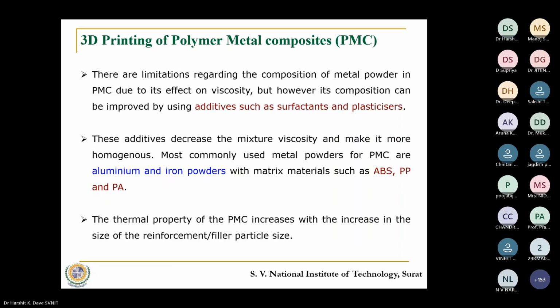So a problem that we face is that the metals or the ceramic particles have very high melting points. So of course we do not cross 150 degrees Celsius when we use polymers like PLA or nylon. Those particles, metallic or ceramic, do not come under the effect of the heat, but they affect the viscosity. So the flowability of this filament during the process becomes a critical issue. The way we add surfactants or plasticizers is something which has to be investigated.